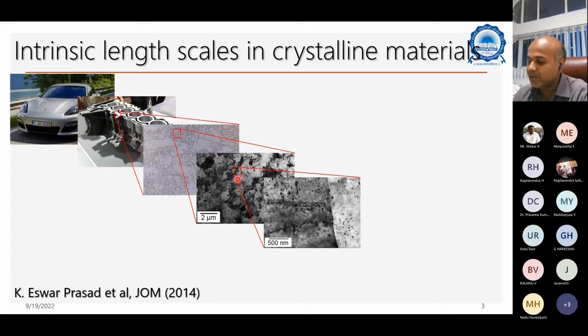So if I dig further, coming down from 2 microns to 500 nanometers, which is one order of magnitude lower, I can see a clear grain boundary here, and I can also see certain features which are very important for mechanical properties, called dislocations, which are one-dimensional defects in materials. The dislocations will come and get blocked at the boundary, which enhances the strength of the material. That is called the grain boundary strengthening mechanism. Okay.